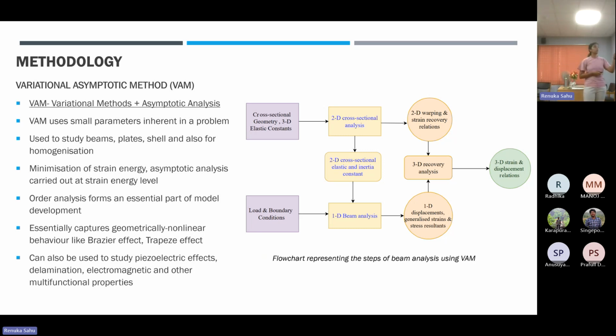Moving forward, we do the 2D cross-section analysis by using this order analysis and minimization of strain energy. We do the 2D cross-section analysis, from which we get the 2D warping and strain recovery relations. And again, we have the load and boundary conditions for the 1D beam.